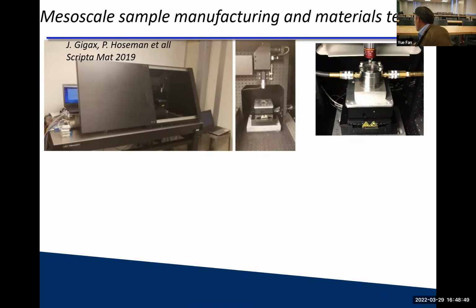And it's actually pretty cool because we can put the sample in this device here. The sample is inside here. And you shoot through a glass, so you've got a glass window you shoot through. So all your radioactive debris is captured in that chamber. So I can have beryllium, toxic material, radioactive material, anything really. Nobody cares that much because it doesn't ever leave my vacuum chamber. And that becomes a consumable and my piece is ready to go.